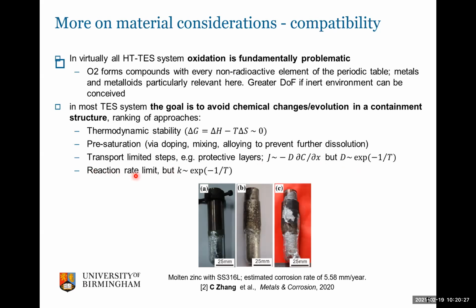And ultimately also limiting the reaction steps, but here, let's say, the reaction constant is typically an Arrhenius type of reaction constant. So at high temperature it's more challenging to limit these reaction rates given the exponential behavior that they have. And here we have a typical example from the literature of molten zinc with a stainless steel containment, and you can notice the estimated corrosion rates here. We are talking about something that is incredibly fast: 5.5 millimeters of thickness of stainless steel corroded per year of operation. So obviously this doesn't comply with the typical life requirements of thermal storage applications at high temperatures.